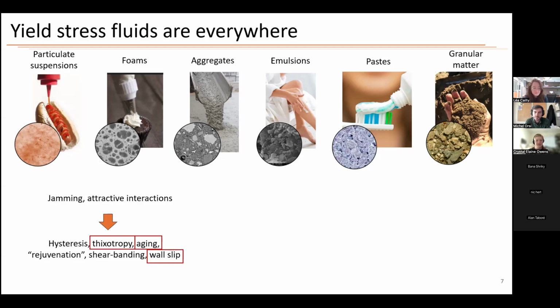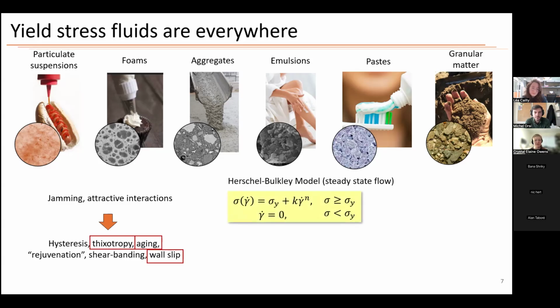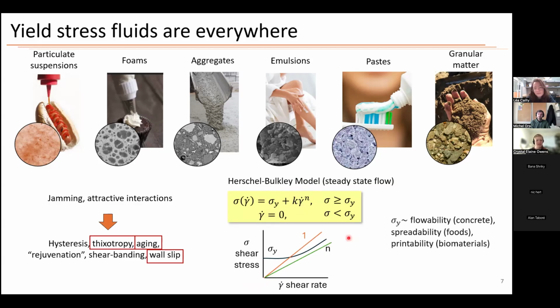And one of the basic ways to understand this is using a Herschel-Bulkley model to model the flow of ketchup. And so this has a yield stress parameter. So below a certain stress, the material will act like a solid, and above this stress, it will start to flow. So it will have a flow curve that looks approximately like this with a plateau region and then flow. And this is in contrast to something like a Newtonian fluid, which will flow under any imposed stress at all, or a shear thinning fluid, which you probably heard of, which will flow, but just with a different slope compared to a Newtonian fluid. And this yield stress parameter itself is very important for understanding and characterizing materials with different applications.